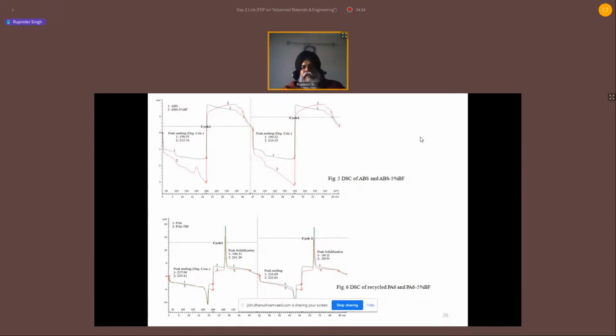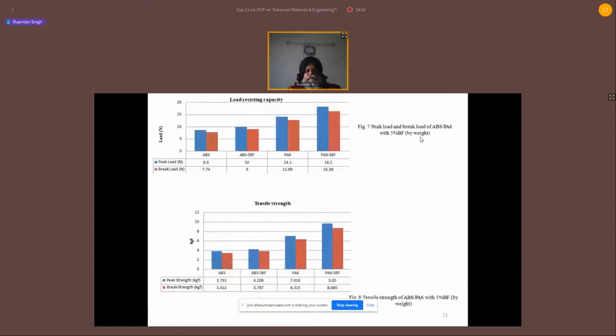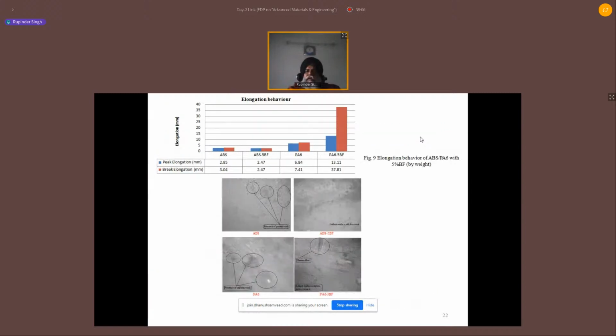Again, here you see we did the thermal analysis, from room temperature to 250, then from 250 back to room temperature, to see how this material behaves. What we observed is that in repeated cycles with the banana fiber reinforcement, the heat capacity was improved. Even the melting temperature was improved, which was observed for both the ABS and the polymer, which is basically a nylon 6 based polymer matrix composite. Similarly, improvements in load, tensile strength, percentage elongation, and of course controlled porosity were observed.